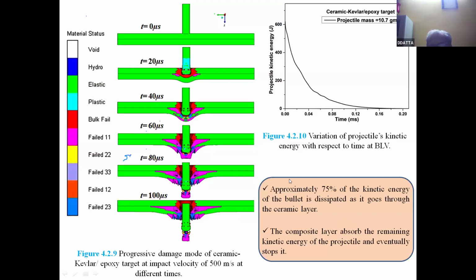What is also observed is that approximately 75% of the kinetic energy of the bullet is dissipated as it goes through the ceramic layer. The composite layer absorbs the remaining kinetic energy of the projectile and eventually stops it, if it can. But if the velocity is still high after passing through the ceramic layer, then of course it cannot sustain it.